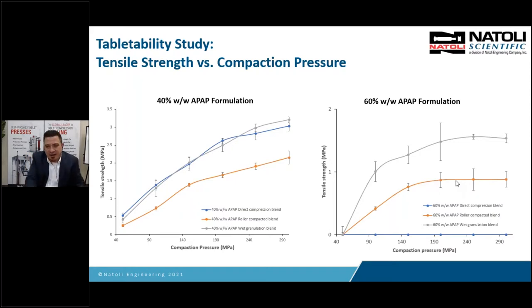But if you take the formula and run this profile, and if it looks like this, and say it's curving over right here, and let's say you're running right in this area of manufacturing, well, you're right at that overcompression area. Maybe some days you got good tablets, and other days you have bad tablets. Let's say purchasing found excipient that's a few cents cheaper per kilo, so they change excipients. Now all of a sudden I'm capping. The moisture content's a little higher today, or the particle size distribution is a little different. Now I'm capping.